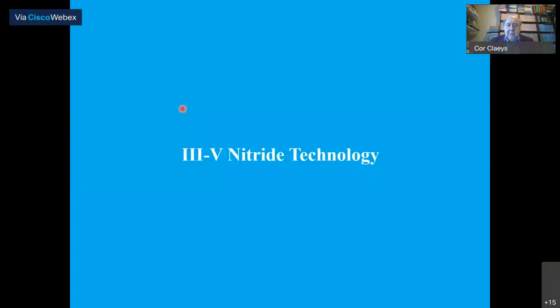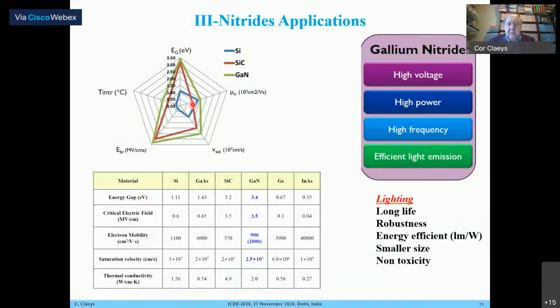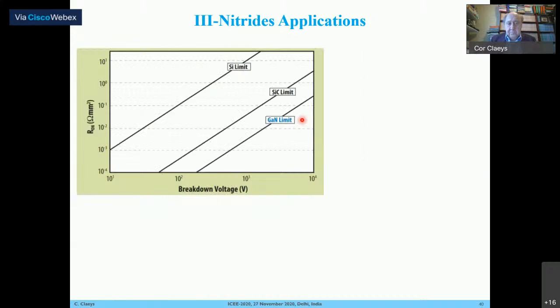Nowadays, there's also a lot of interest in III-V nitrides. And here you see a comparison between the blue silicon, the brown silicon carbide, and gallium nitride, the green one. And you also have a table with the different data. I'm not explaining that again because of the timing, but with gallium nitride, you can achieve high voltages, high power, high efficiency, and very efficient light emission. So that means that is going to result in very, very promising device components.